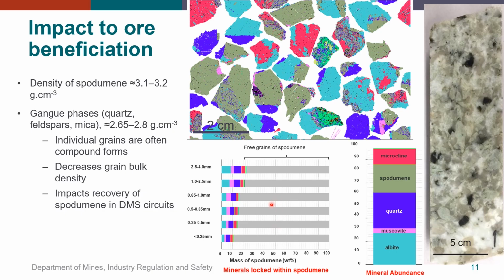The bar graph shows the proportion of free spodumene and minerals locked within spodumene with decreasing particle size. While spodumene is mostly liberated in all the size fractions, up to 20 to 25% of the spodumene grains contain intergrowths or inclusions of quartz and feldspar in the coarse fraction. And even in the finest fraction, there's still about 10% of inclusions and intergrowths within spodumene.